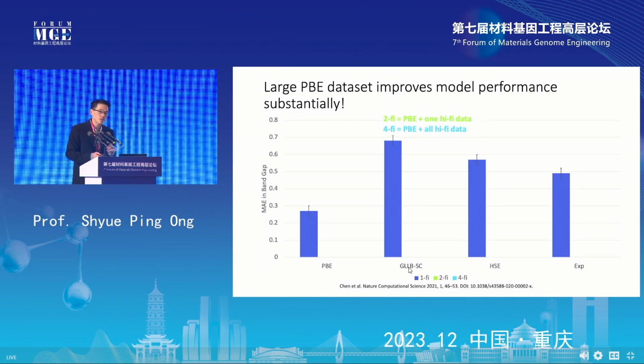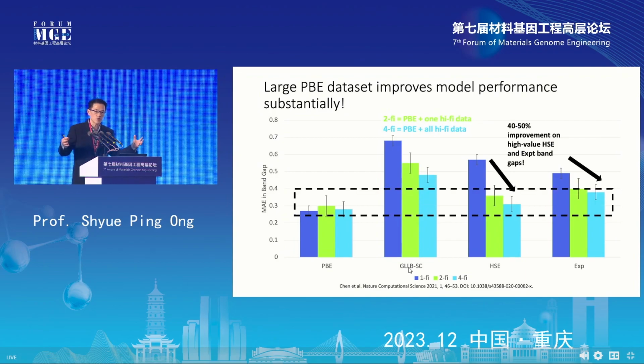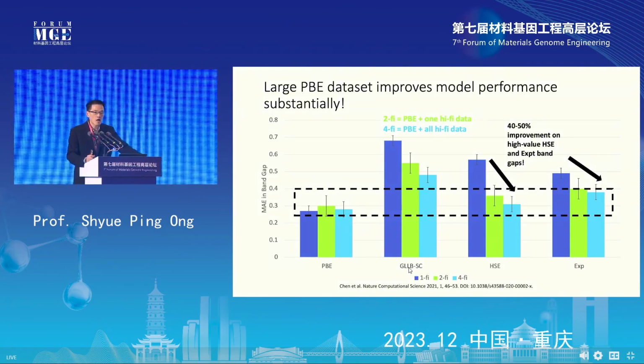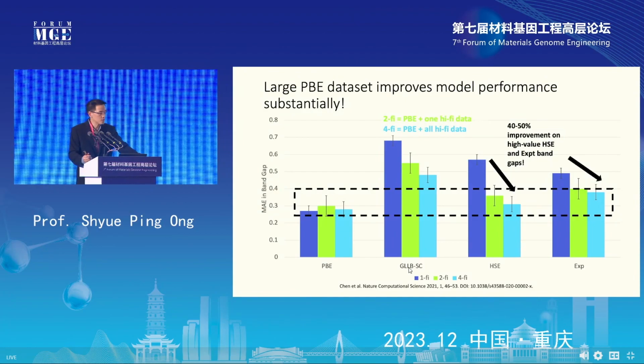Now, by using a multi-fidelity approach, in other words, we combine all the data together, we can get a 40 to 50% improvement in the prediction of our high-value band gap information. So HSE band gaps and experimental band gaps, we get this 40 to 50% improvement in the prediction accuracy without actually having to measure any more experimental band gaps or having to calculate more HSE band gaps, okay? So in other words, we are getting something for nothing just by leveraging the chemistry that is learned in our materials graph network models, okay?